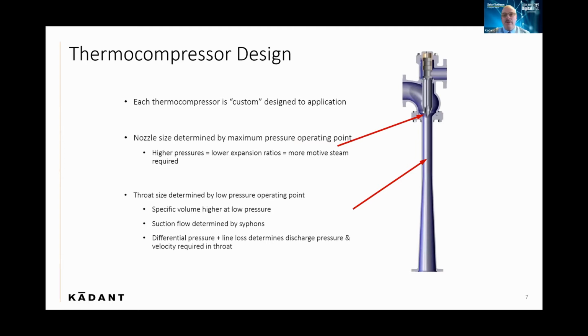In the thermocompressor itself, it's the high pressure condition that determines the size of the nozzle, because that's where we're going to need the most amount of high pressure steam. But it's the low pressure condition that will determine the size of the throat in the diffuser. That's because the low pressure condition will have the highest specific volume. So what we like to do for Yankees is to try and narrow that gap as close as possible. Try and bring your low pressure condition to be almost the same as your high pressure condition.